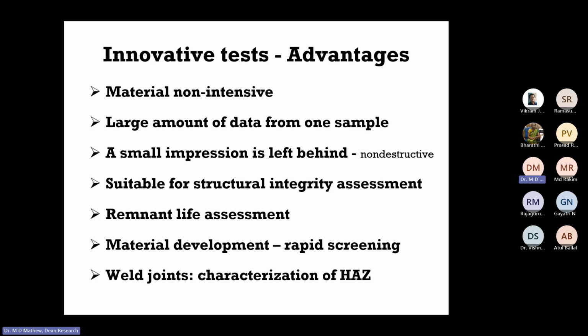And another big advantage of these methods is that you can characterize the creep properties of different microstructural zones of weld joints. We all know that a weld joint, ultimately the integrity of a weld is decided by the properties of either the weld metal or the base metal or the heat affected zone, and weld is always considered to be a weak link. So it is difficult to determine the properties of each of these zones. Either you make a big weld pad and then prepare weld metal samples, or from the parent material you prepare base metal samples. But it is very difficult. Or you make a sample which will contain weld metal, heat affected zone, as well as the base metal.